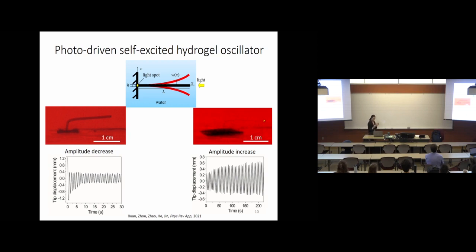The interesting behavior we discovered is that if you have a hydrogel cantilever beam, and I have a light fixed from the side, we actually observe self-excited oscillation. So you have a light, then the hydrogel can oscillate by itself, for a very, very long time. And more interestingly, on the left case, you see the amplitude starts from a high value and decreases. But on the right it starts from a low value and actually can increase. For both cases, after a long time, the amplitude saturates and becomes a stable oscillation.